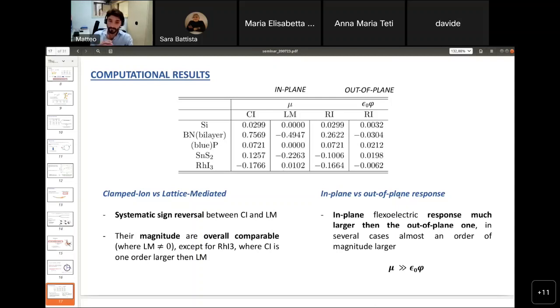But maybe the most interesting finding in this case is that the in-plane response turns out to be much larger than the out-of-plane one, and in many cases almost one order larger. So even if this effect, the in-plane effect, is an unconventional effect that is active only in a certain class of materials, we find that it can be much more useful than the previous one.